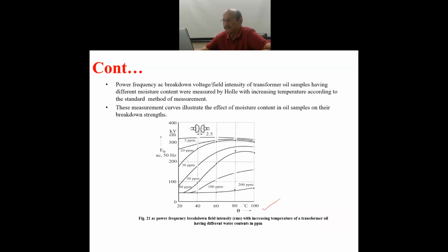Just to give you an idea, imagine when the humidity content is only, in the topmost curve, of the order of 5 ppm, that is 5 parts per million, and you measure at a normal temperature of, say, 30 degrees centigrade. Can you imagine, you are measuring kV per centimeter of more than 300. This is the practical strength, as I was mentioning, of the order of 350 kV per centimeter.